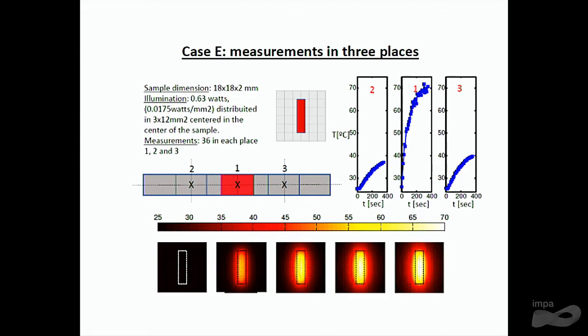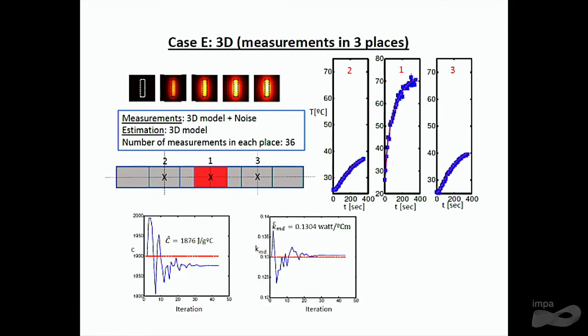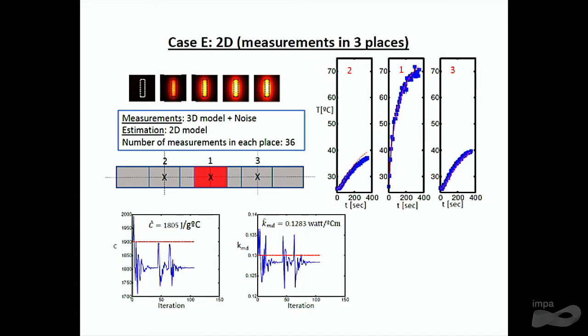We measure the three quantities, temperatures. In the center, we have the measurements we had before, and on the sides, we have these 2 measurements that, of course, give you smaller values. And we are going to use these generated values using the 3D model to estimate parameters. The parameters estimated using this configuration are much better than the ones that we obtained before, not only for a 3D model, that is something obvious, but also for the 2D model. As you see, the error is around 5%.